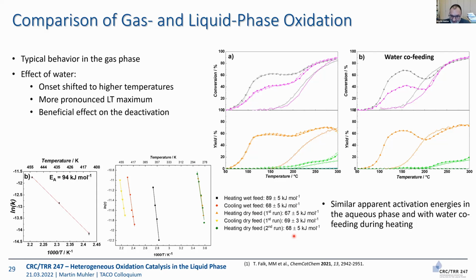Now, in between working under dry conditions in the gas phase and really working in water, what's in between is then using wet feed. That means we added water to 2-propanol and oxygen, checked what the effects are, and we saw that actually adding water is beneficial. Then we do some formal kinetic analysis to see analogies. And indeed, we got similar apparent activation energies in the aqueous phase and with water co-feeding during heating.